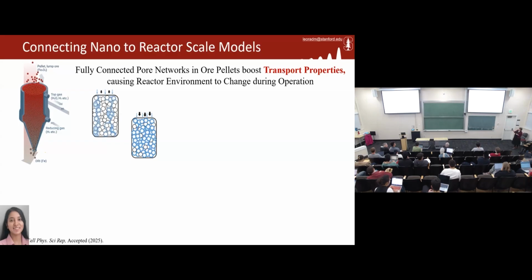So, of course, if you have a reactor that's not stuck, i.e. there's good permeation of gases, then effectively your gas can get to all the different pellets that react in your system, i.e. you can go to completion in your chemistry. Whereas if you don't have good permeability in your reactor bed, ultimately it will fail because you will have the gas only going through the path of least resistance to get to the end of the reactor. So she felt that permeability was a nice proxy variable to be able to describe at a larger length scale how the attributes of porosity at the nanoscale would translate to reactor design variables.